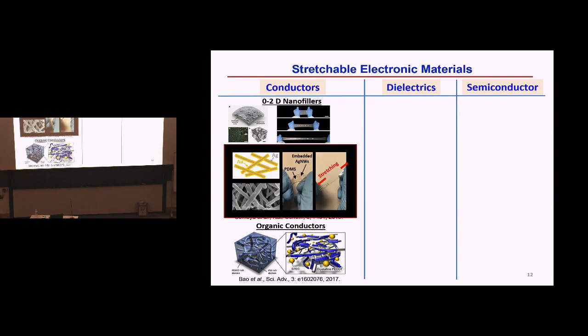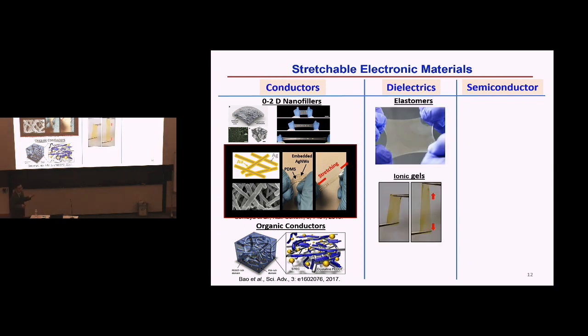What my group has been very interested in over the past few years is utilizing these nanowire materials. There are two major reasons for this. First, nanowire materials have a high aspect ratio, so they are relatively long with a small diameter. That way, the percolation threshold is fairly low, which retains mechanical stretchability with a lower loading of nanowire materials. Another reason we're interested in this approach is that we can modify the surface of these nanowire materials. It's very critical for transistor devices that we have a good match between the semiconductor and the conductor to make an ohmic contact instead of a Schottky junction. So this is very important. Now looking at the dielectric material, there are a lot of rubbers readily available, and they are insulating materials.